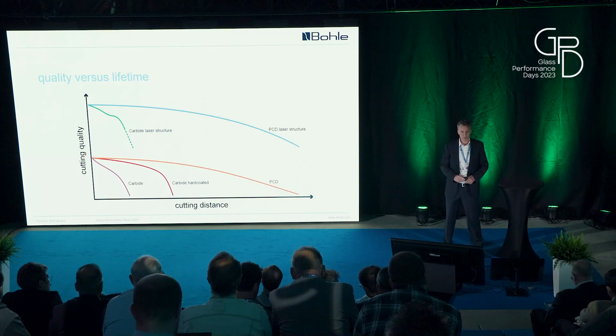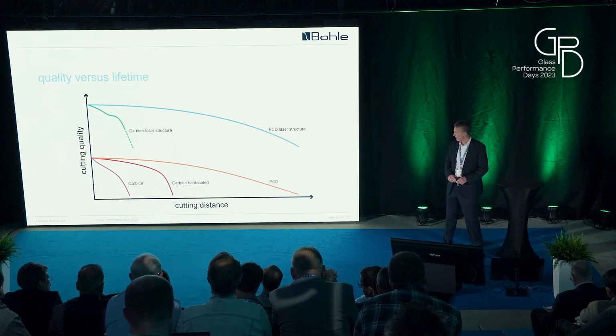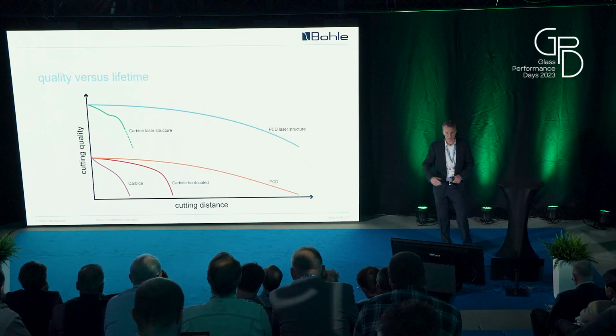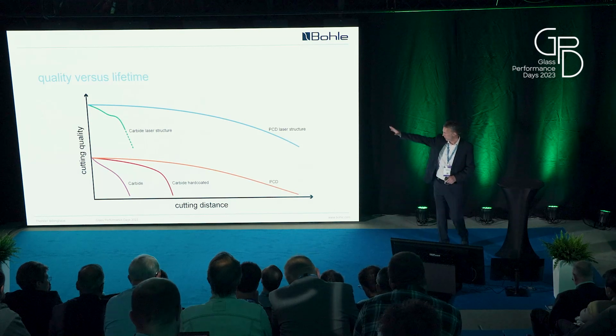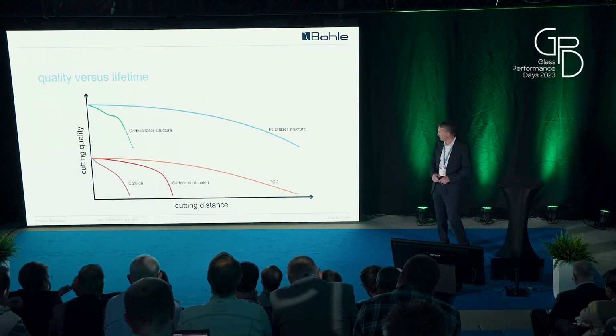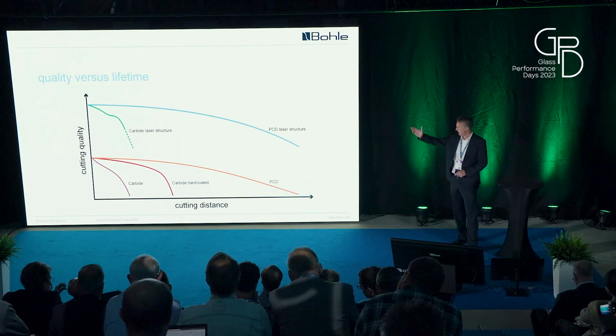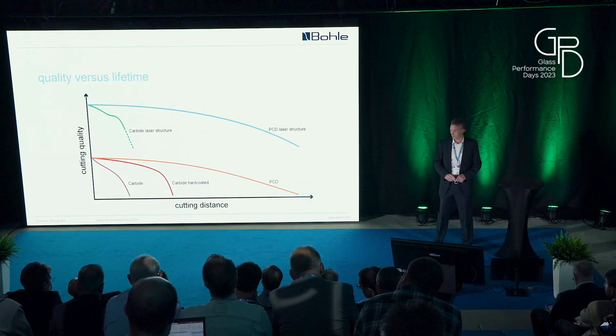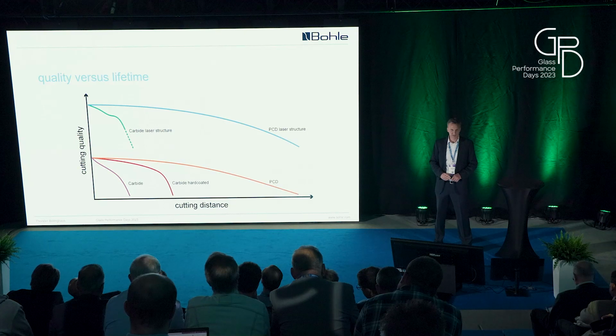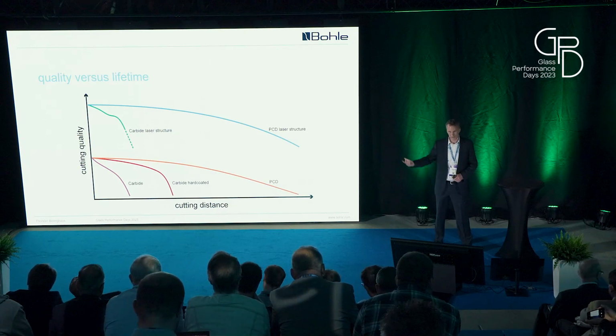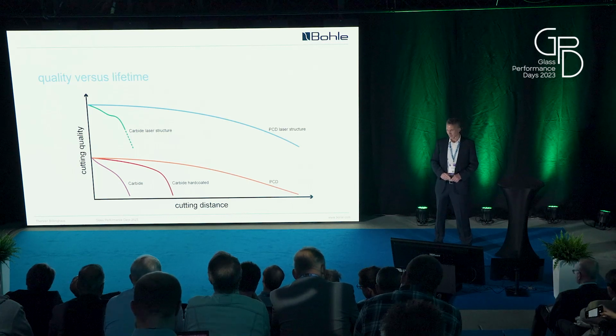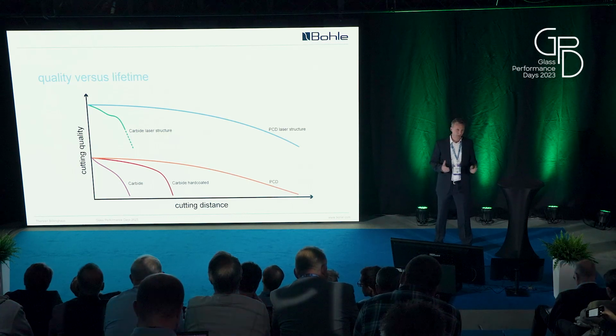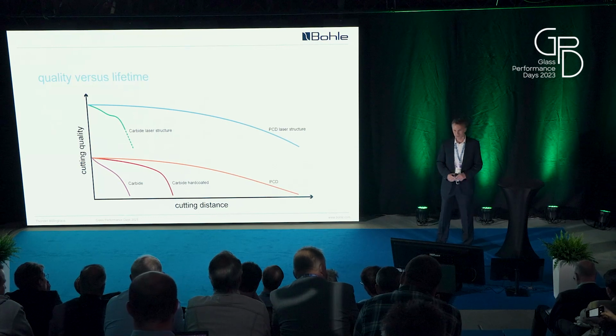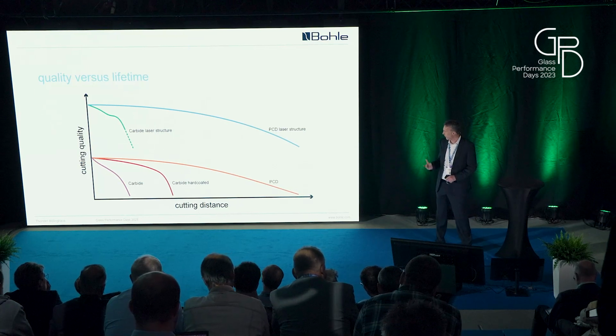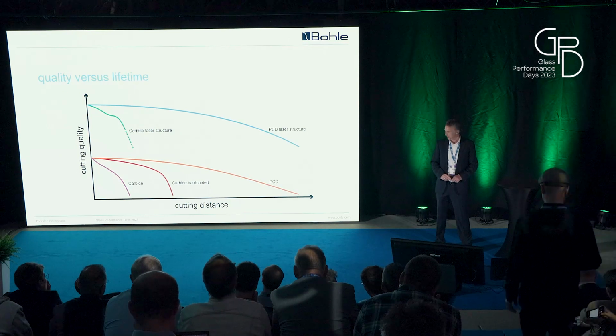With the laser structure, with the recessed cutting edge, you are in a completely different world in cutting quality. That's indicated by the higher level you see on the left side. And as you see, the structured carbide wheel has a slightly longer lifetime than the classic carbide wheel. So there are clients that use it for a very long time. You can, but later on it will just have the same properties as a normal wheel, and that's not why you use it. You use this carbide wheel because you want these extraordinary properties, so you would change it.